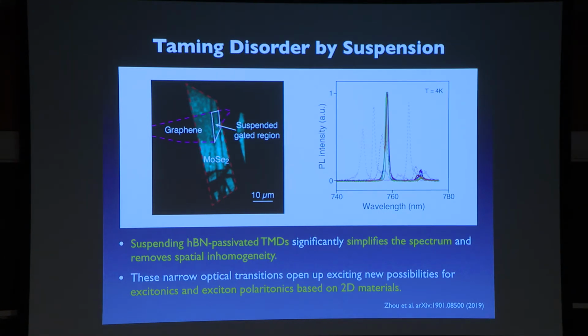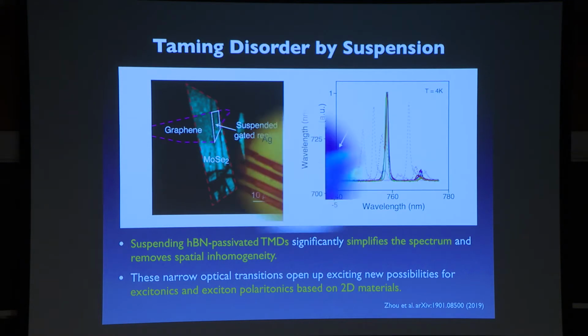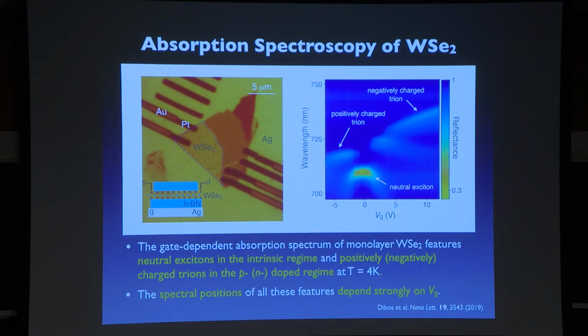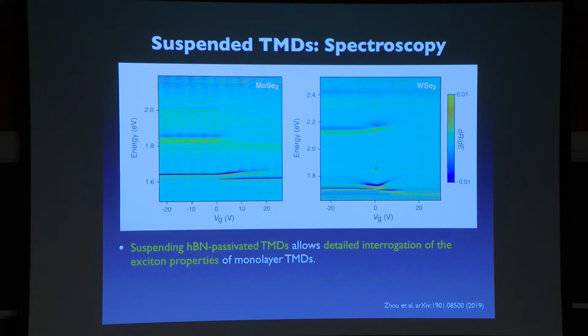OK, so you can actually do a bunch of different things, like passivating them using other wider bandgap materials and suspending them. You can make these spectra as nice and as sharp as possible. And then once you do that, you can use that fact to do lots of different types of things, like spectroscopy. These are the typical spectra that people have gotten without all those optimizations. But by optimizing the properties of those materials, you can start to get much sharper lines, which are much better defined, and